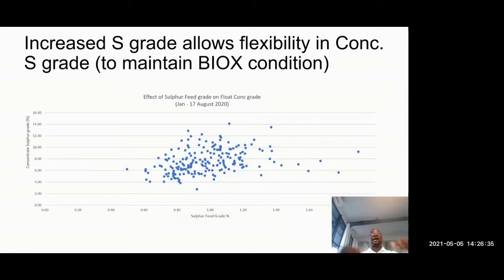Then how do you use it in our current circuits? Thankfully, we are scoring. This graph is showing the effect of sulfide grade on the recovery. The more you can pull the mass of the sulfide into the concentrate, the more your sulfide concentrate goes up, and with it, the gold concentrate goes up. Most of the gold here, as I told you, apart from the quartz, is really in the sulfide, and the sulfide is mainly arsenopyrite.